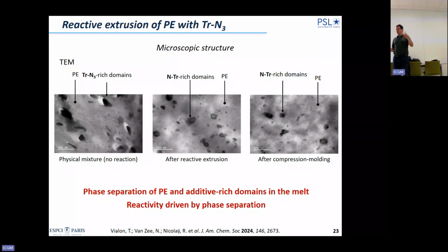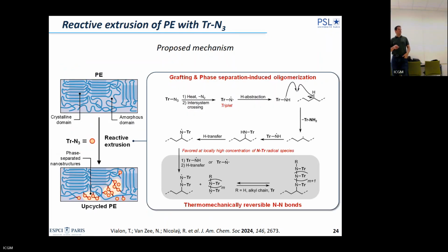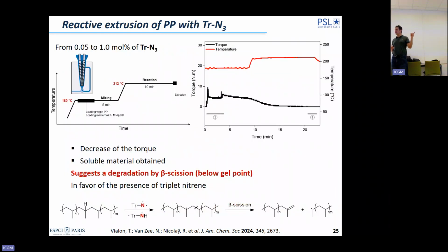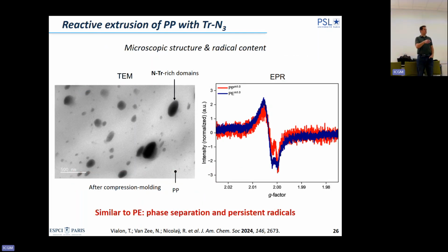It is phase separated, and we show this by TEM, and the additive is not dispersed in PE before it reacts and after it reacts. And then I'm going to skip this. If we do the same thing with PP, because it is a radical process, we don't make a network, we just make a polymer chain of lower molecular weight because we make a lot of beta scission. But we were still able to show that we graft the additive onto PP and we still create our polyazine bond and we have radicals, as you can see by EPR.